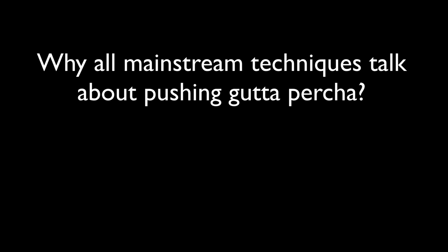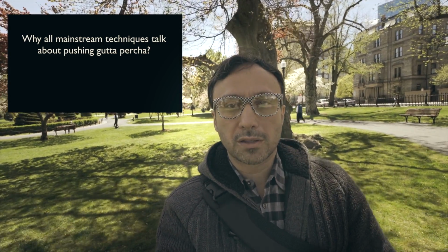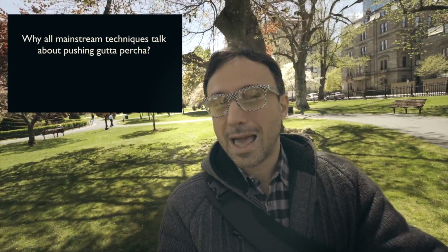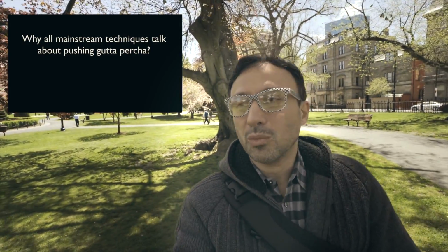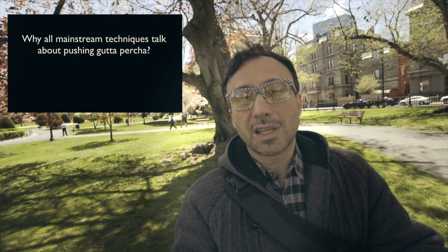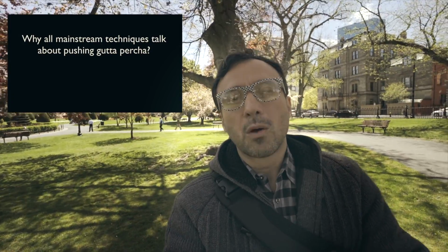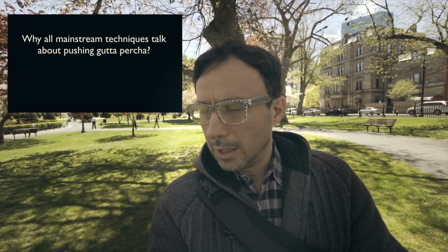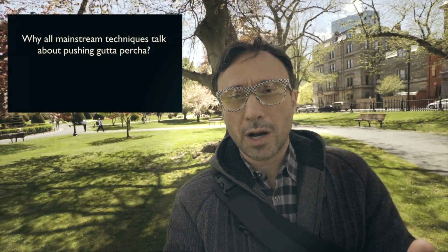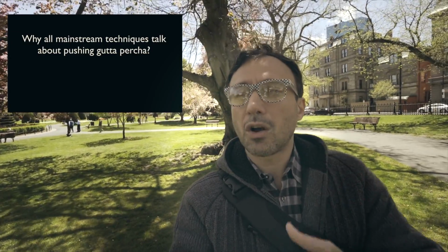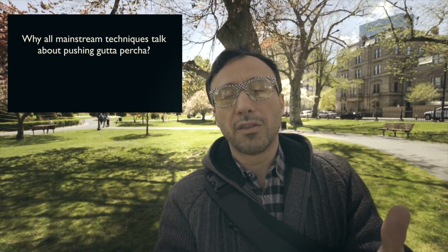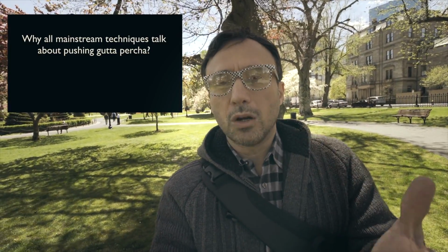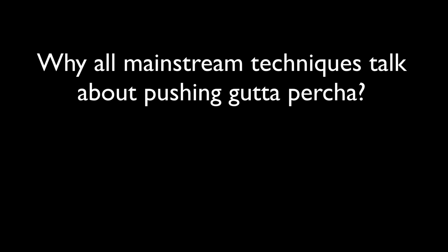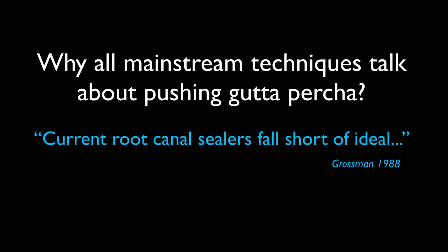Well, when I became a resident, it finally became clear to me that the main reason why we're doing all these pushing of the vertical and lateral and all different ways of moving the gutta percha is because of a study that was done by Dr. Grossman, where he looked at all of the available sealers that were on the market at the time of his study, and he found that all of the zinc oxide eugenol sealers and all the resin sealers that were available at that time were severely deficient in sealing the root canal.